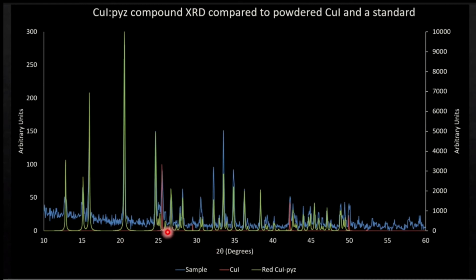Well, so in interpreting these, what you're looking for is peaks that overlap. So copper iodide is in red, and the sample is in blue. So we can see here that the sample shares some peaks with copper iodide, but not all of them. So then there's other peaks that are shared with this red copper iodide and pyrazine polymorph that is from a literature value for this compound. And you can see those peaks overlap, green with blue, and that verifies that we do in fact have what we think we do.